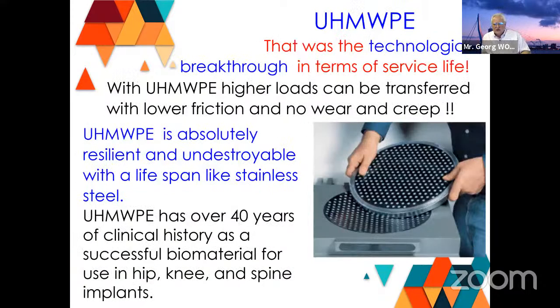It was a kind of technological breakthrough in terms of service life, because with this material you can transfer much higher loads with a low friction, and you have no wear and no creep. The material is absolutely resilient and indestructible. It has no aging effects. It has a lifespan like stainless steel. So since we know the material, we found not any change of the material if you are within the load limits of these approvals or even further.